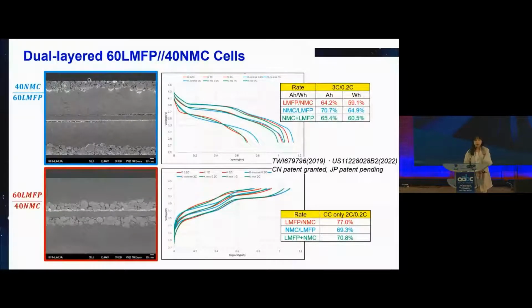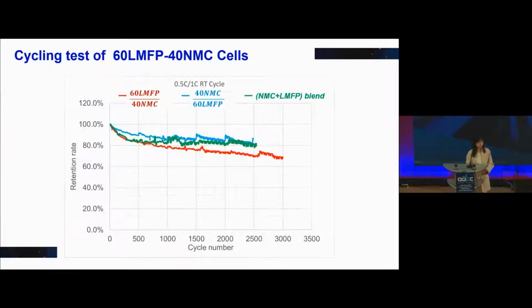Let's turn our attention to the impact of the electrode structure on the electrochemical performance of the cell. In addition to studying the composite cell, we also examined the dual layer cell with either NMC or LMFP in the top layer, just like the SEM shows here. You can see that the dual layer cell with the NMC in the top layer, which is marked in blue, had the best discharge power capability. Conversely, the dual layer cell with LMFP in the top layer had the best charge power capability. Among these cells, we also observed that the dual layer cell with NMC in the top layer, the blue part, had the best cycle life performance.